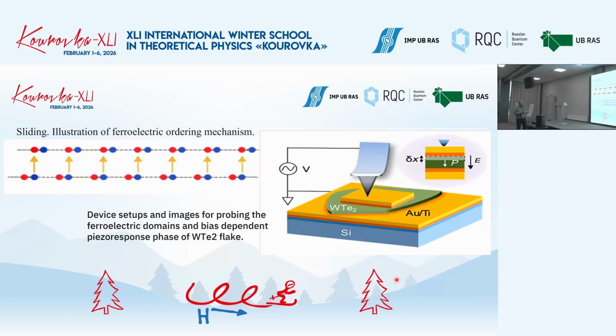In this slide, I will try to illustrate a sort of basic idea of the very unusual ferroelectric ordering in these structures. It's called sliding ferroelectricity. And the idea looks as follows. You want to arrange the shift of the atomic structure in the plane of the layers so as to get the dipole moment perpendicular to the layers. Why does it happen?